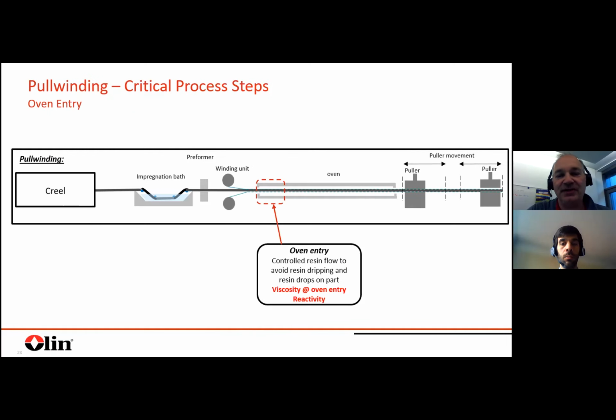So the next critical part is the oven entry. Here you need to control the resin flow to avoid resin dripping. And this is, I would say, the most critical point, the question which I see most, it's really related to this point. It's related to the resin in the way of the viscosity at the oven entry and the reactivity, because there you start the gelation and the reaction and the viscosity build up.